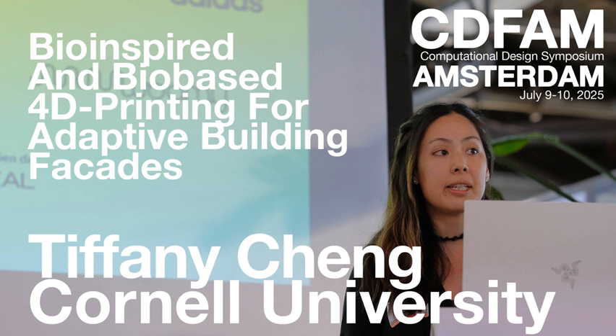We also measured the squeezing forces of the 4D printed material system and compared the different combinations of the two mechanisms. So here you can see on the bottom, the helix mechanism by itself without anything else generated pretty low forces. And the addition of these pocket mechanisms in low and high densities generated increased forces to varying degrees. But the most effective strategy for generating squeezing force was to delay the actuation of the pocket mechanisms.